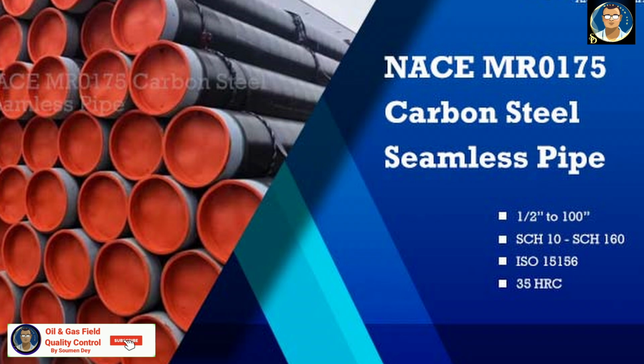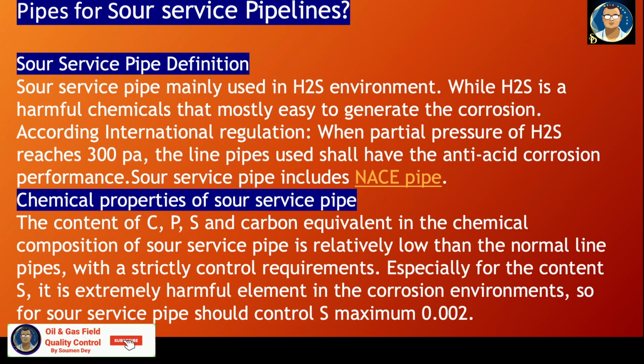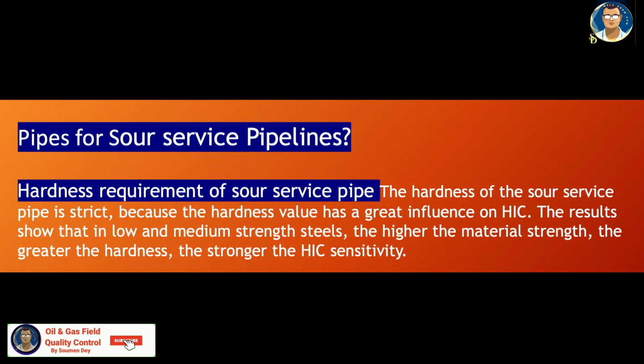Chemical properties of sour service pipe. The content of carbon, phosphorus and sulfur and carbon equivalent in the chemical composition of sour service pipe is relatively lower than the normal line pipe, with strictly controlled requirements. Especially the content of sulfur, it is an extremely harmful element in the corrosion environment. So for sour service pipe, sulfur should be controlled to a maximum of 0.002%.